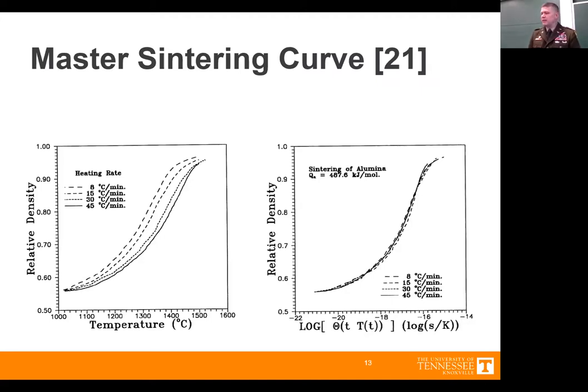This again is using the master sintering curve to try and make some of those predictions. The chart on the left shows multiple different sintering trials at different heat rates, with relative density on the y-axis and temperature on the x-axis. You can see that the different heat rates achieve different relative densities as a function of temperature. The faster we heat it, the more quickly it densifies, essentially. Or the less dense it is at the same temperature, maybe is a better way to say it. But what's interesting is that by taking that set of data and applying it through the equation I showed on the previous slide, those curves all condense to one curve. That's the graph on the right.